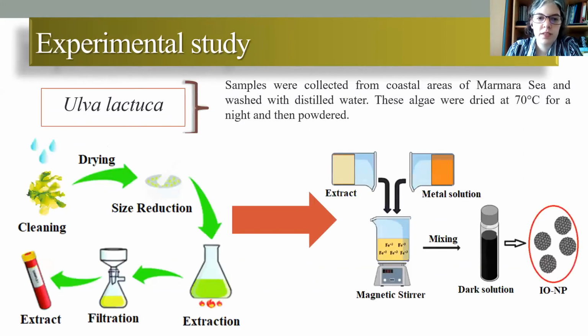In the experimental study, we used Ulva lactuca as a raw material, which was collected from the coastal areas of the Marmara Sea. It is considered waste, which is why we chose this material. The algae were first washed with distilled water to remove impurities, then dried at 70 degrees Celsius overnight and powdered.